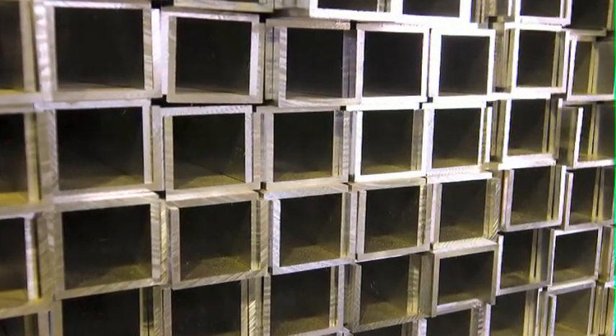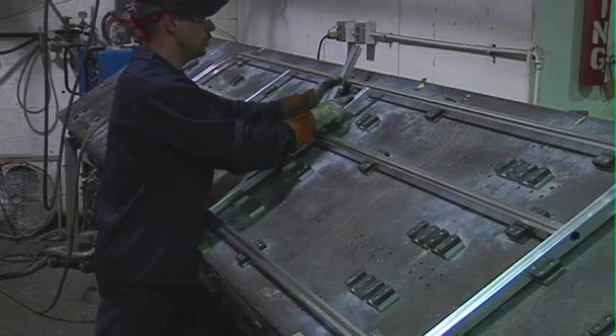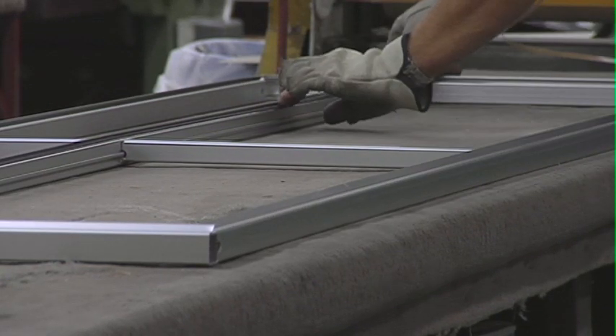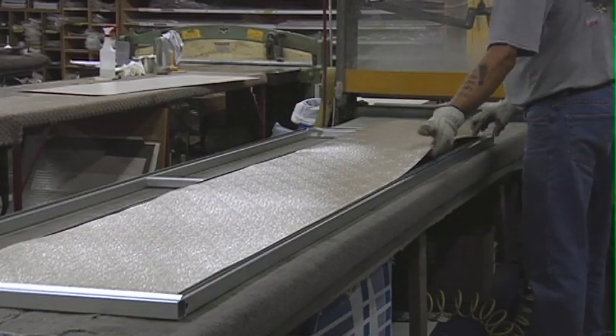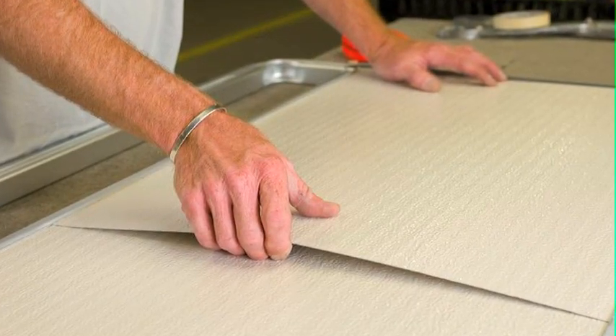Every mooring cleat is attached through a structural cross-member for additional strength and security in extreme weather conditions. The Harris Float Boat fence is fabricated from Harris-designed extrusion dies. Our welders use customized jigs for each model, and fence joints are MIG welded on at least three sides. We anodize the fences, gates, and ladders after welding, which not only ensures a weld that will survive the outdoor elements without discoloring or oxidizing, but also results in a stronger, less porous weld. Our custom-designed graphics are applied with a high-strength adhesive. Before attaching the fence panel to the rail sections, foam tape is applied to any location where the panel will contact the rail support structure, eliminating rattles from metal-to-metal contact.